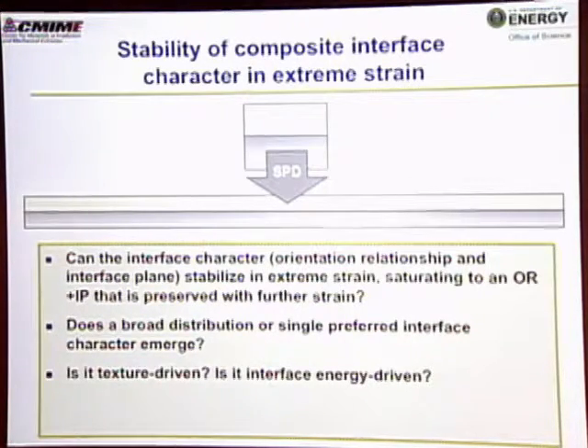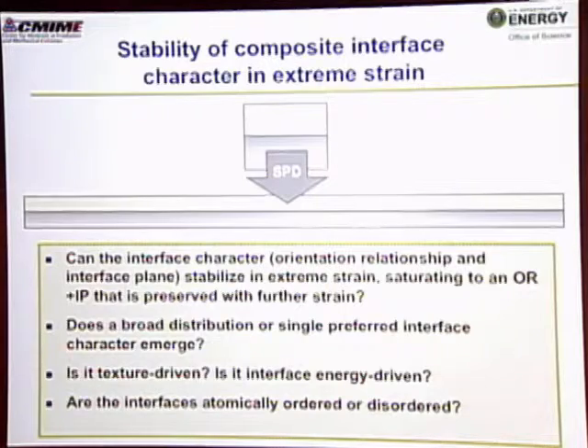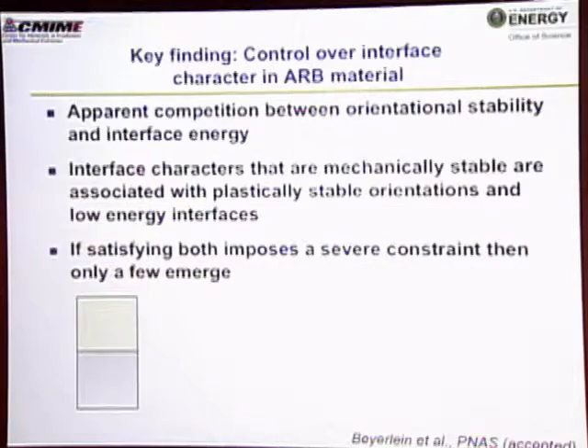Is it texture driven, that is driven by slip like in rolling? Or is it interface energy driven, as you would see in physical vapor deposition? And are these interfaces sharp and ordered or all jumbled up? So the key finding here, I won't get into the details of this, but what you have is this competition between orientational stability and interface energy. What does that mean?